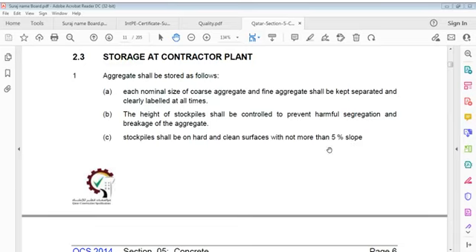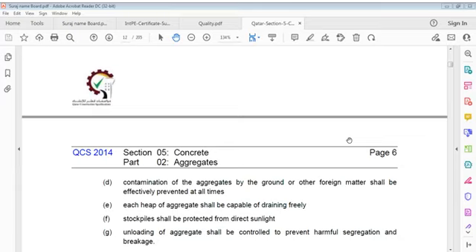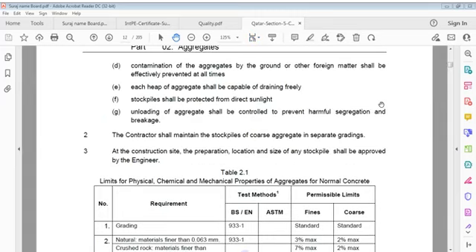Stockpiles shall be on hard and clean surface with not more than 5% slope. Contamination of aggregate by ground or other foreign matter shall be effectively prevented at all times. Each heap of aggregate shall be capable of draining freely. Stockpiles shall be protected from direct sunlight. Unloading of aggregate shall be controlled to prevent harmful segregation and breakage. Contractor shall maintain stockpiles of concrete coarse aggregate in separate gradings.